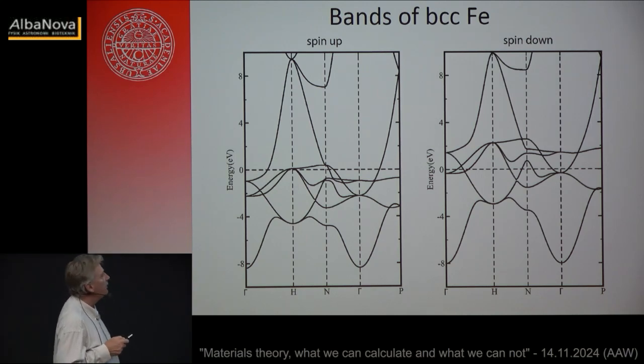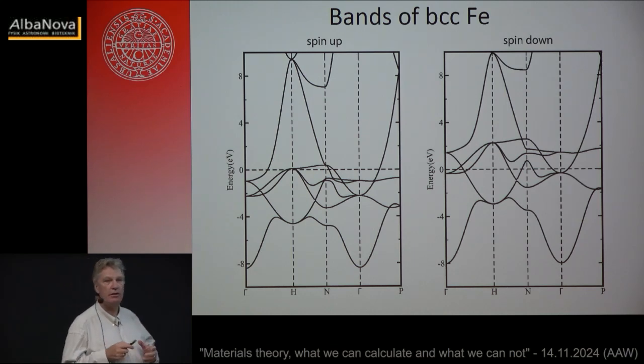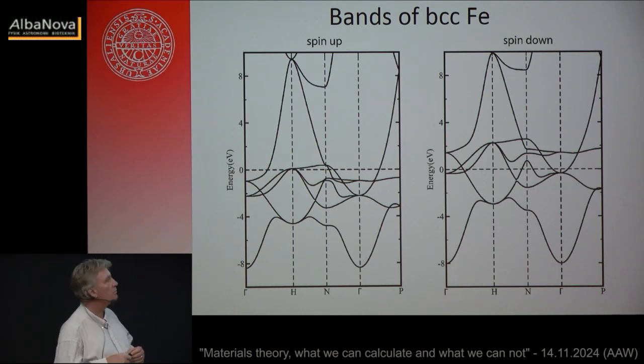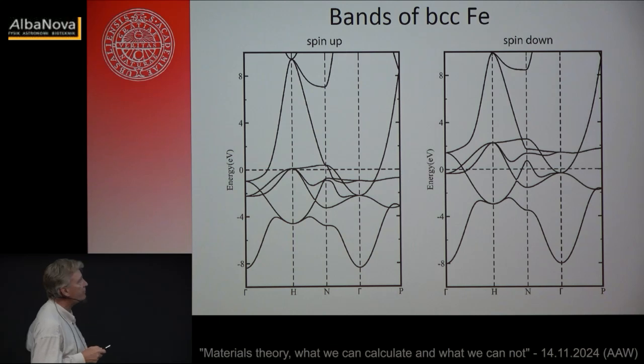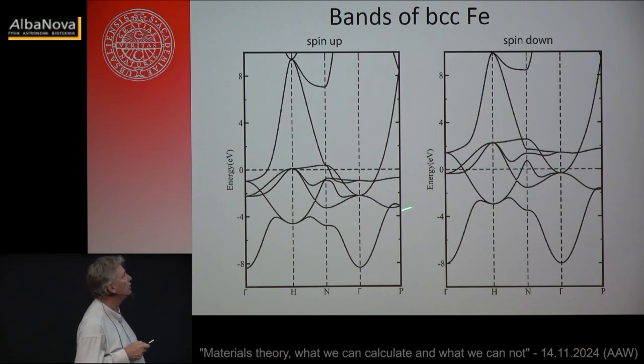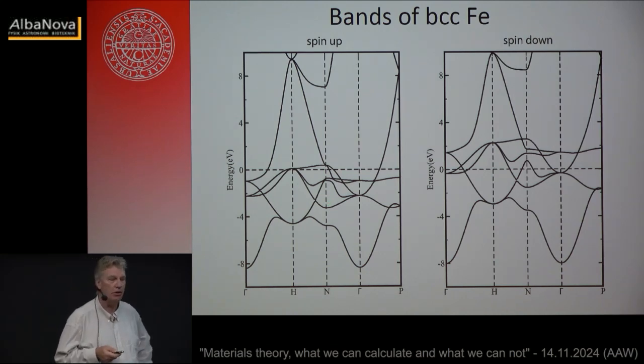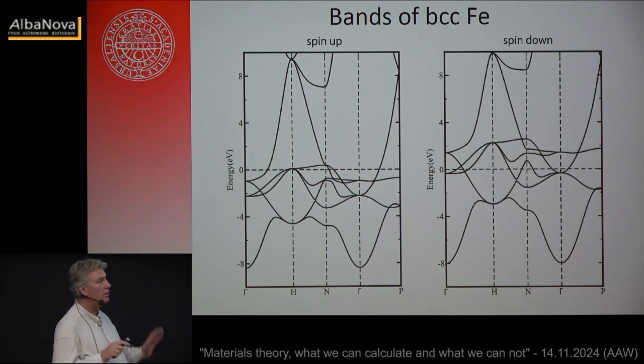But with dynamic mean field theory, and I'll come to that at the end of the talk, then these bands, these electron states can be squeezed and can be tweaked, they can be broadened in such a way that they finally start to look like what you find from an ARPES measurement. Already in the first papers that Kohn and Sham and Hohenberg wrote, they said, don't view these energy eigenvalues now as something that is experimentally detectable. It's just a Lagrange multiplier to ensure that equations don't go haywire in the electron density. So it's just something that is introduced to make the particle number constant or not go out of control.